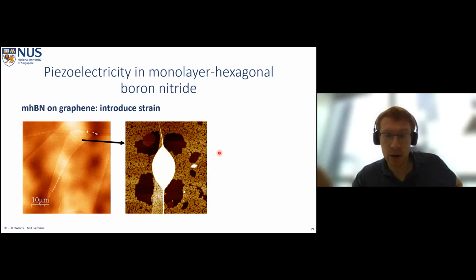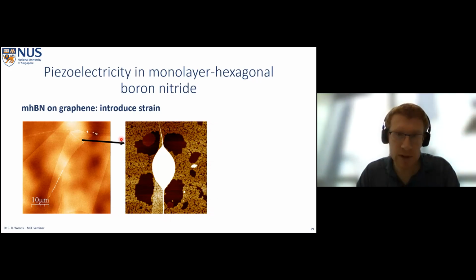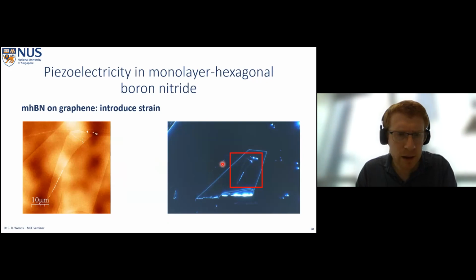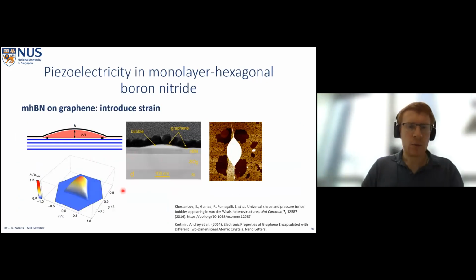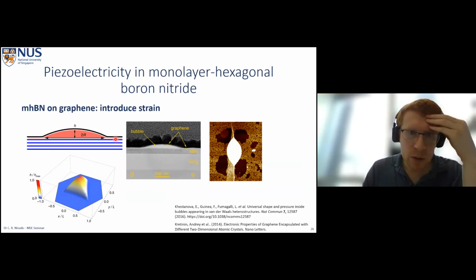This got us thinking that these materials can withstand huge strains, and that the monolayer form is expected to be piezoelectric. Maybe these bubbles, which, as you say, are epicenters for these relatively large forces, are actually producing a large effect. So this was the serendipitous moment for this project. But the second reason that motivated us to use these bubbles is, if we go to this picture here, the bubbles iron out these very clean regions.